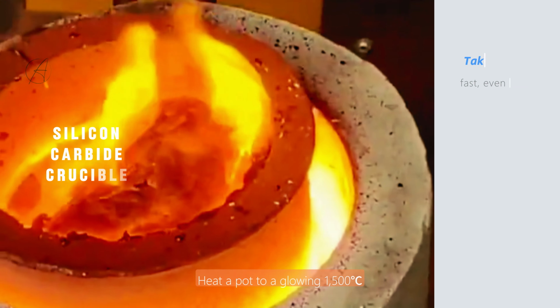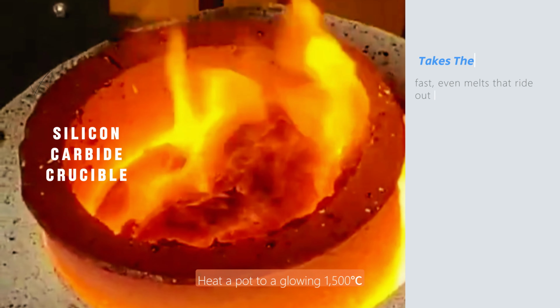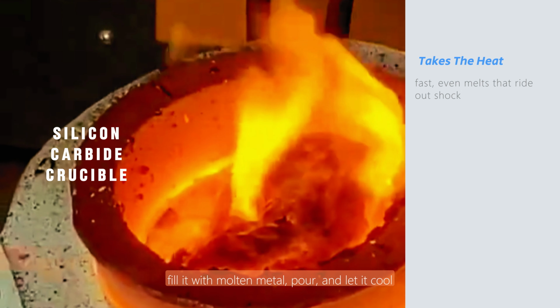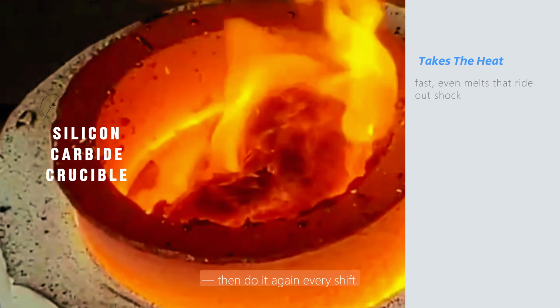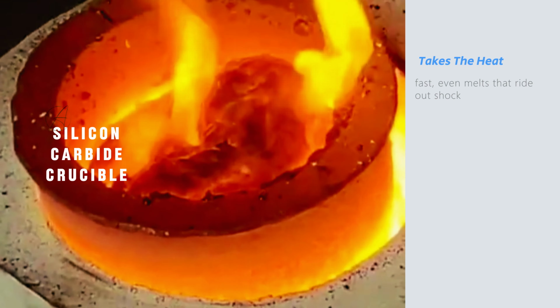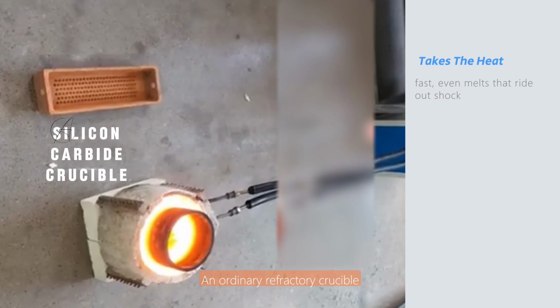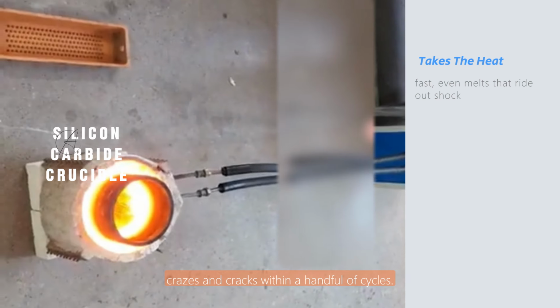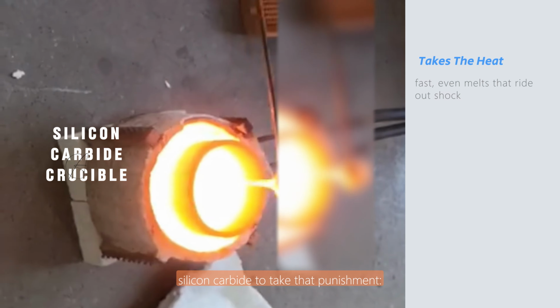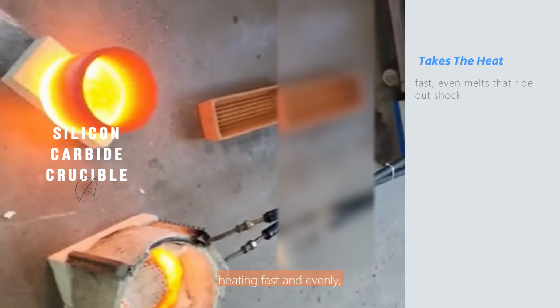Heat a pot to a glowing 1500 degrees, fill it with molten metal, pour, and let it cool. Then do it again every shift. An ordinary refractory crucible crazes and cracks within a handful of cycles. The dark cylinders here are cut from silicon carbide to take that punishment, heating fast and evenly, and riding out the thermal shock that splits lesser pots.